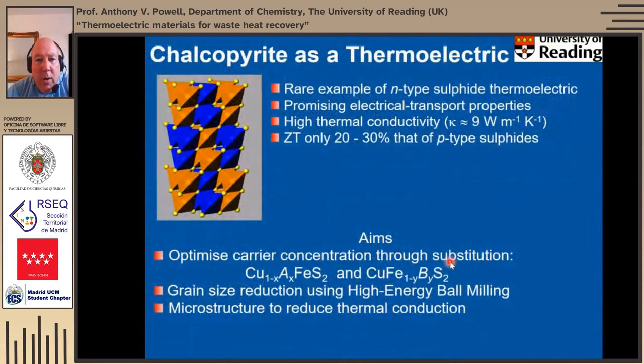Chalcopyrite is a really quite interesting thermoelectric material because it's a rare example of an N-type material, and it has quite promising electrical transport properties, but very poor thermal conductivity. So its thermal conductivity is similar to an unfilled skutterudite, about 9 watts per meter per Kelvin, and consequently its figure of merit is only about 20 to 30% that of the best P-type sulfides.